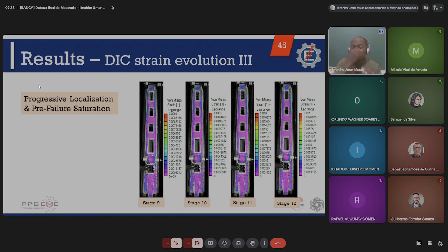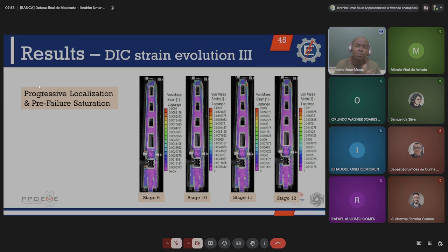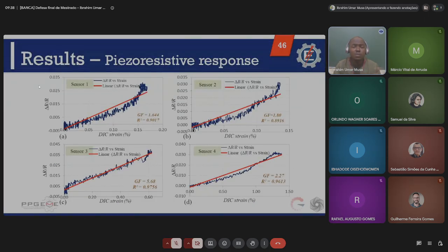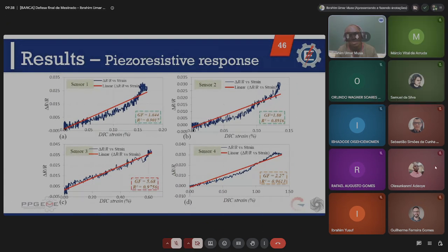And for the piezoresistive response of the 4 different sensors in pairs, we were able to see that the first pair displayed relatively consistent results, as presented here by the gauge factor and linearity, while for the second pair we can see a clear margin in terms of the gauge factors. Now this was a result of the misalignment or asymmetry introduced by the load fixtures during experimental testing.